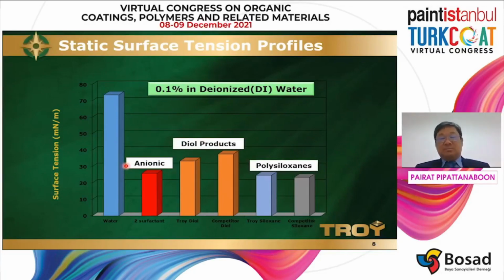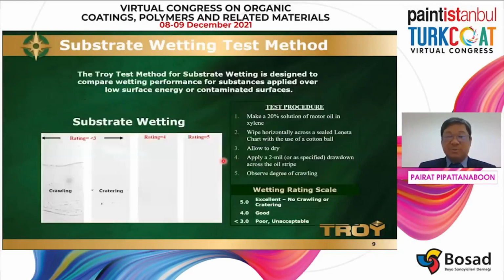So by far, polysiloxane has quite low surface tension at about 24 dyne per centimeter, and with only 0.1% of the wetting additive added into the DI water, you can reduce the surface tension from 72 to 24. Anionic is not so bad, around 25 to 26 dyne. Diol is about 38 dyne per centimeter. That's the ranking of surface tension reduction, particularly for just these 3 chemistries that are industry benchmarks.